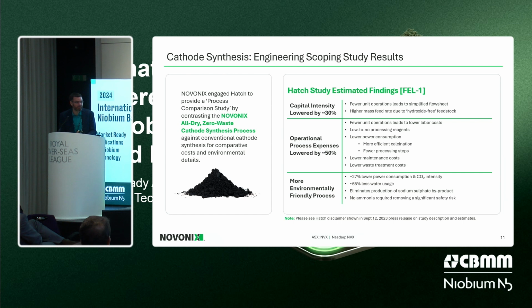In terms of OpEx, we're decreasing the intensity by roughly 50%. Again, fewer unit operations, fewer operators required to maintain the equipment, and lower power consumption, lower waste treatment costs, et cetera, right? So it makes a whole lot of sense to go all dry. And on the environmental side, roughly 27% lower power consumption, decreasing processing water use by roughly 65%. You still need water to cool equipment as you scale, but the water does not touch the powder itself. And there's no ammonia handling requirements or sodium sulfate being generated. So it makes a whole lot of sense to go in this all-dry, zero-waste stream rather than making cathode the conventional way.